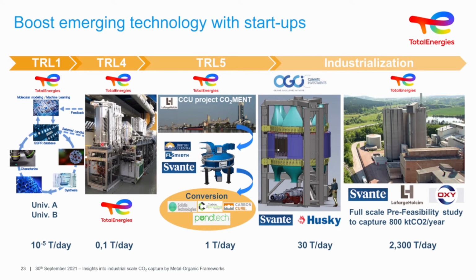And we look at this cycle. We test the materials that are sent to us. And we've been carrying out cycles now for over 4,000 hours on one of their materials. So this process demonstration unit is a way forward to go to higher scale. So this is 0.1 tons of CO2 per day captured, 1 ton, 30 tons.